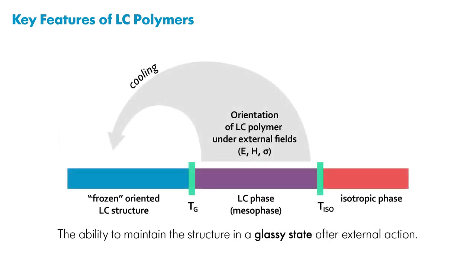The second important feature of liquid crystalline polymers is the ability to maintain the structure in a glassy state after external exposure. In the temperature range between the glass transition and transition to the isotropic phase, the various fields and light can change the structure of the phase or orientation of the molecular fragments. Cooling of liquid crystalline polymer film below glass transition temperature enables fixation of the modified structure in the solid glassy state. For most liquid crystalline polymers, glass transition temperature lies in the range slightly above room temperature up to 100 degrees, and isotropization temperature up to 200 degrees or more.